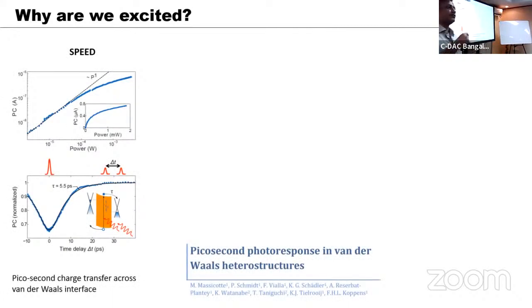Why am I excited by this development? First of all, speed. If you take superconducting nanowires, people use them because you can get good thermalization times, jitter and other parameters. Here we are talking about a system in which the charge is going from one layer to the other. That's the main speed-limiting time. So we are talking about a time scale at least a factor of 1,000 lower than that